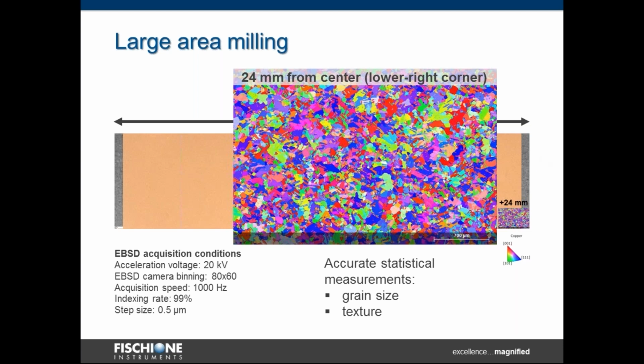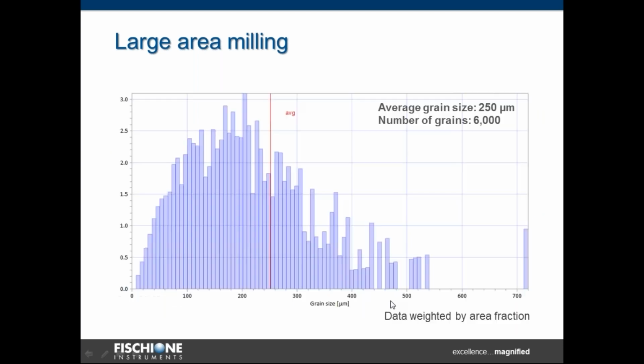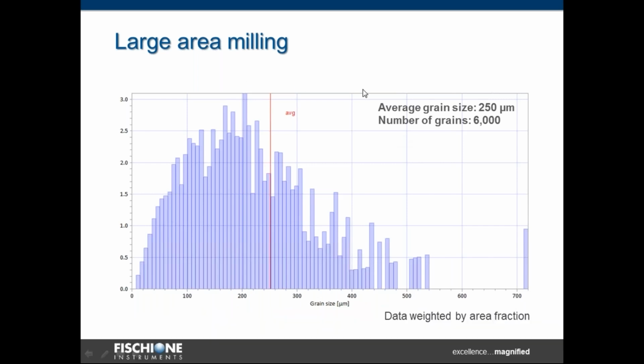what you can get from so huge an amount of data collected from a huge sample like that, 50 millimeters wide. You can improve your statistical measurements like grain size or texture. Here is an example of the average grain size that we calculated for our copper bar, which is 250 microns. It was calculated from 6,000 grains, and as you can see, this is only from a small fraction of the sample.